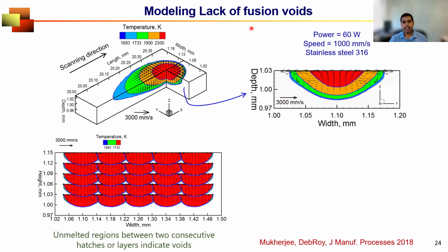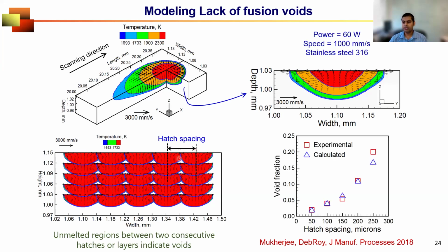So what do I mean by lack of fusion void? Lack of fusion voids are this white region, where two consecutive molten pools are not properly fused together and create an empty region. How can you minimize this? One way to minimize is bringing them close. And that distance is called hatch spacing. That means if you reduce the hatch spacing, you should reduce the lack of fusion void, which is very consistent with the experiment. You see, void fraction is significantly less at a low hatch spacing.